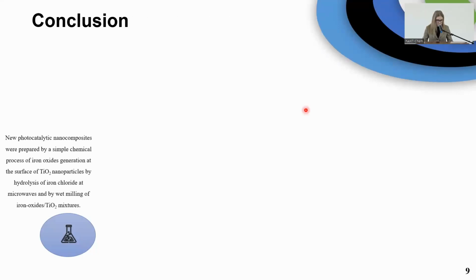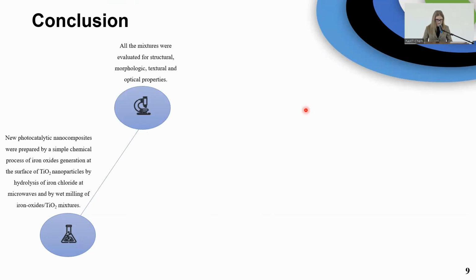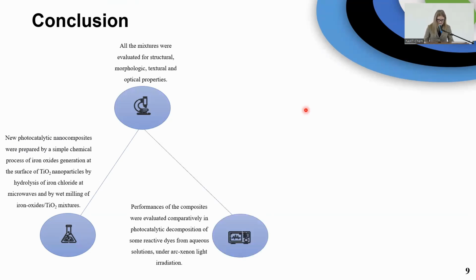In conclusions, new photocatalytic nanocomposites were prepared by a simple chemical process of iron oxide generation at the surface of titanium dioxide nanoparticles by hydrolysis of iron chloride at microwave and by wet milling of iron oxide with titanium dioxide mixtures. All the mixtures were evaluated for structural, morphologic, textural, and optical properties.